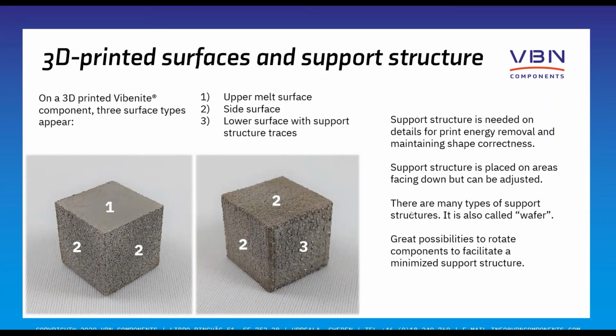If we look at surfaces, I mentioned that we have rough surface, and you can see here on the picture to the left, we have 3 types of surface. We have the upper melt surface, we have the side surface, that is the most typical, the largest area is the side surface of the component. And then you have number 3, which is a lower surface with support structure traces.